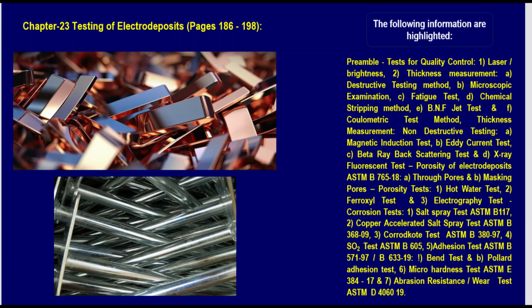Porosity of electrodeposits as per ASTM B765-18. A. Through pores, and B. Masking pores. Porosity test. 1. Hot water test. 2. Ferroxyl test. And 3. Electrography test. Corrosion test. 1. Salt spray test ASTM B117. 2. Copper accelerated salt spray test ASTM B368-09. 3. Corrodkote test ASTM B380-97. 4. SO2 sulfur dioxide test ASTM B605. 5. Adhesion test ASTM B571-97, otherwise B633-19. And bend test, Pollard adhesion test, micro hardness test ASTM E384-17. And 7. Abrasion resistant and wear resistant test ASTM D4060-19.